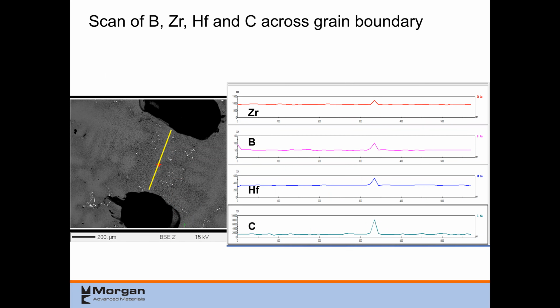This is a material that was made that they were trying to figure out the grain boundaries, and they suspected that zirconium, boron, hafnium, and carbon were going to be present in the grain boundaries because of how they were making this material, but it wasn't really obvious using EDS. So we looked at it under the electron microprobe, and we knew the grain boundary was somewhere between the two black blebs that are there. That's just Sharpie that they marked on the surface. And so I tracked through and found exactly where the grain boundary was based upon the small amount of those elements that I found there.